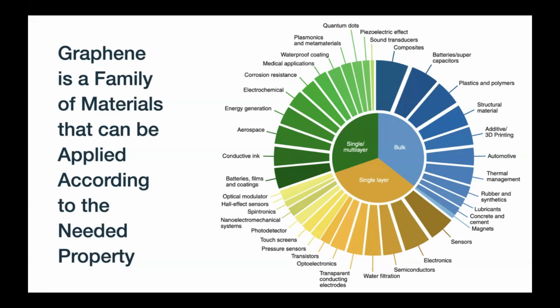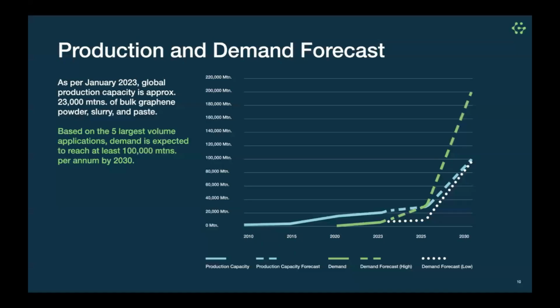We've come across quite a few people in these past years who said we've tried graphene, but it didn't work. And one of the most common reasons is you didn't have graphene at all, or it wasn't the right type of graphene for your application. Secondly, when adding graphene, especially in these bulk applications, we find that using very small amounts of graphene is more effective than using larger amounts, which is counterintuitive. Most people would think if I've used graphene and it didn't work, I'll try adding some more and see if that works better. When in fact, it's often the case, you're going to get a better result by actually using less graphene.